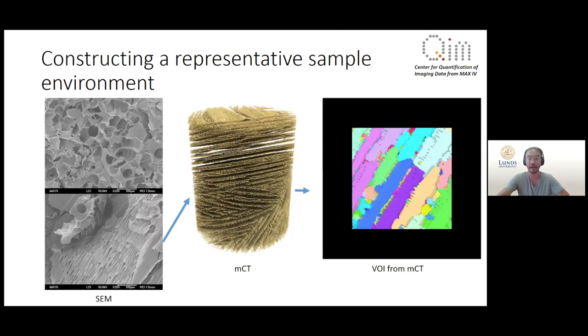We have worked a lot with freeze drying and we have quite a good idea on how a freeze-dried amorphous material looks like when we freeze dried them in a vial. But when we tested our sample environment it turned out quite differently. Here is the tomography picture of our sample environment freeze-dried. This kind of structure is a typical phenomena called directional supercooling, and this kind of structure is more connected and can easily create the path to the vacuum, resulting that they keep their primary structure and preventing the movement to form the secondary structure.